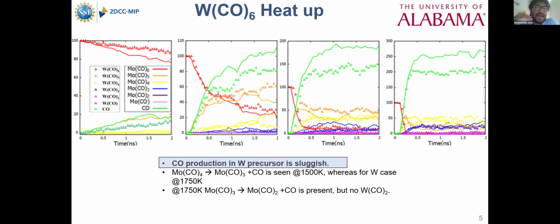And we can see that for the molybdenum ones, the carbon monoxide production was actually higher than the tungsten one. So we can say that the carbon monoxide production in tungsten precursors is actually sluggish. And we can also see that some reactions are happening at lower temperature in the molybdenum case, but in the tungsten case, they're happening at higher temperatures, such as molybdenum tetracarbonyl to molybdenum tricarbonyl plus carbon monoxide. That happens at around 1500 Kelvin, but around 1700 Kelvin, we see the same reaction as seen at 1750 Kelvin.